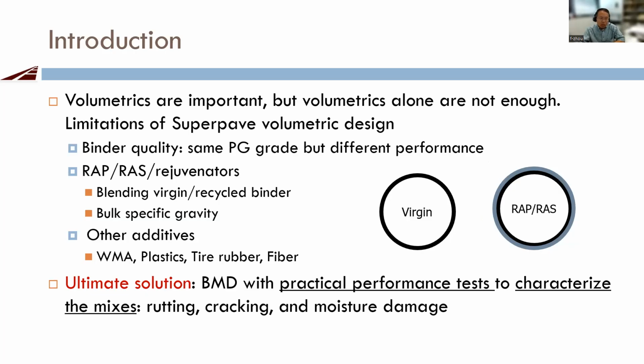We all know volumetrics like air void, VMA, VFA, all these are very important for pavement performance. But at the same time, we all know volumetrics alone are not enough. So there are at least several limitations with the current Superpave volumetric design. The first one, when we talk about binder quality, in every state, they may be using PG 64-22 or PG70 or PG76, different performance grade binders. The problem is with the same PG, for example, you may have 2 or 3 PG 64-22. When you go through the volumetric design, they may give you exactly the same asphalt content, but the binder itself may be significantly different. We're going to show you some examples at a later time. They have the same PG, but they potentially have completely different cracking resistance.